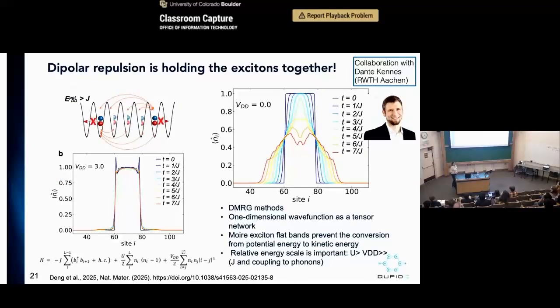One of the things that are very surprising to us is that these Mott states actually last for 80 nanoseconds, which is a very, very long time for an exciton, because a lot of things can happen in the solid state lattice. You can have phonons, a lot of things can destroy the coherence between these excitons. And so one of the questions was why these excitons can stick together for 80 nanoseconds. So this is a question that we then turned to our theory collaborator, Dante Kennes. And Dante can do this sort of DMRG simulation, many body simulation, looking at how this Mott state behaves.